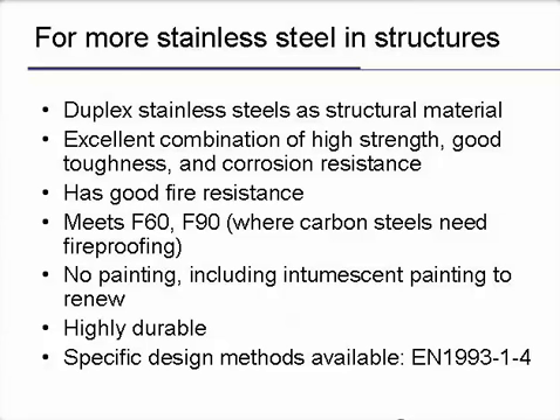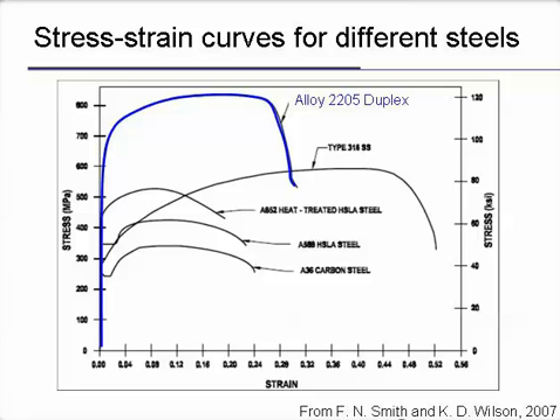So now in Europe, you have one code that is doing this, the part 1.4, and here is the alloy, the duplex. You can see here you have a 316, and where A36 is, down here. So this is austenitic stainless steel, and this is the duplex one, so you can have quite good resistance with these special steels.